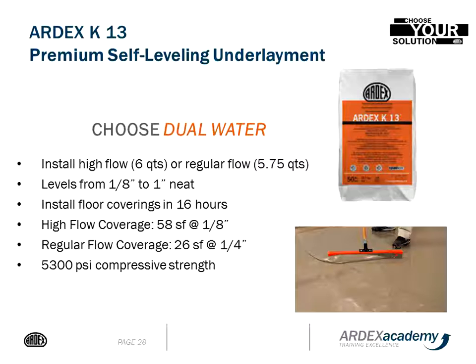In other applications where you might be going deeper, you want a little bit more body to the leveling material because you're going deeper and you don't want it running as much. You can use the regular flow ratio at 5 3/4 quarts per bag. That difference in water changes the viscosity to the point where it still heals itself to create a flat surface, but it's not as flowing, and you're able to maintain it in thicker applications at different elevations a lot better than something that was more liquid. So the dual water is really an advantage.